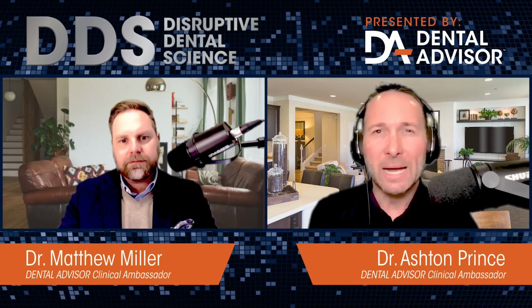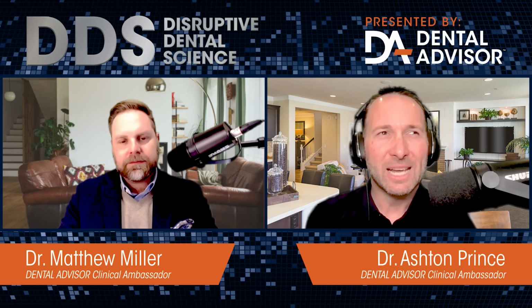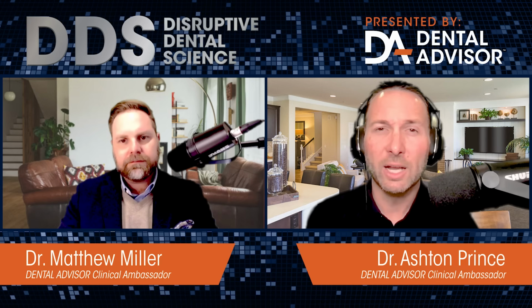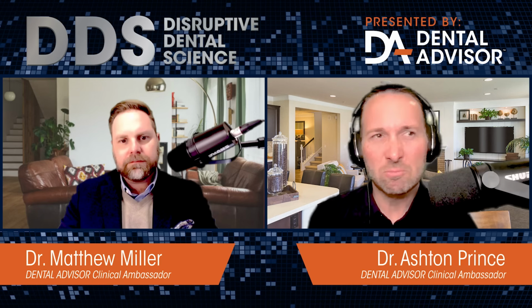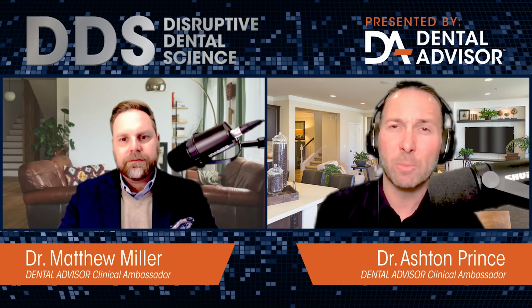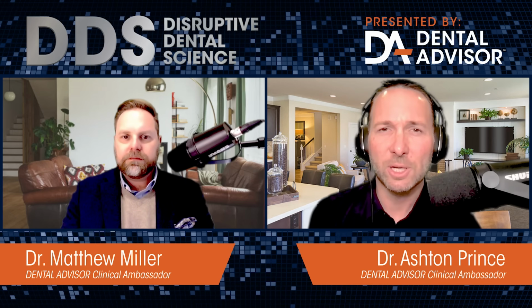In my case, we did this with Dental Advisor during this evaluation that we had. I believe by the time the evaluation was done, I saw about 112 restorations that were done between you and I and others. The amount of change that I saw over a 2 year period, maybe one, maybe two had some small little discrepancies, and they weren't even dramatic to start off with in the first place. But the vast majority of them all maintained that same color they had when I first seated those restorations.